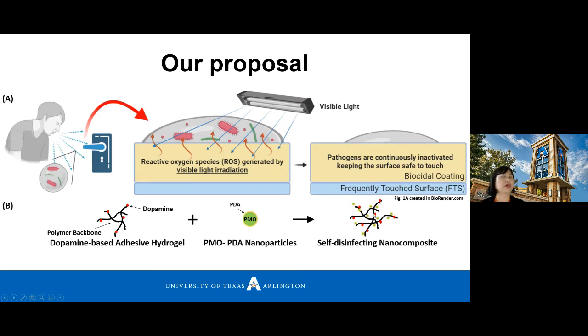We call this material a self-disinfecting nanocomposite, because when you just shine the light, it will self-disinfect. It will kill the pathogen, virus, and bacteria continuously when you shine the light on the surface coated with this material over time. So you don't have to apply something like bleach several times, or use disinfectant solution all the time on the surface. You just coat it one time and shine the light, and it will stay there over time.